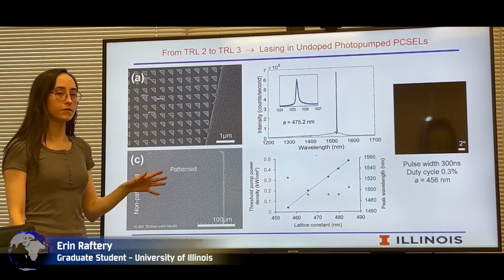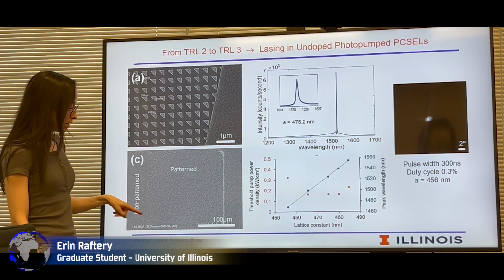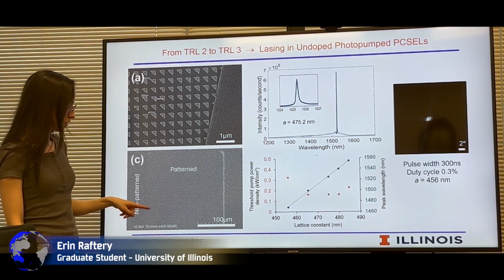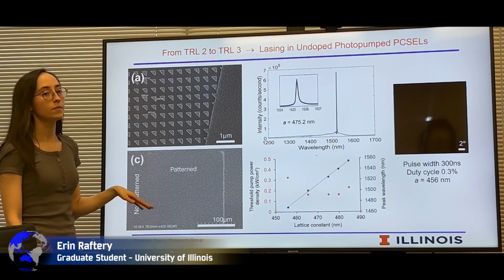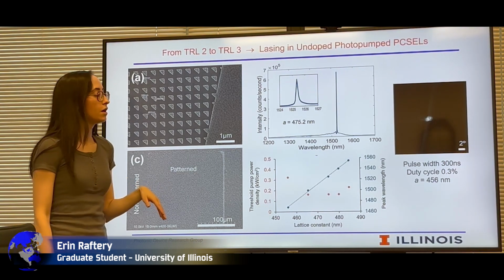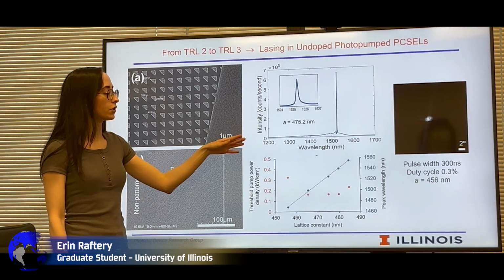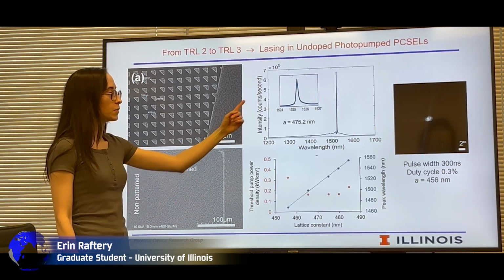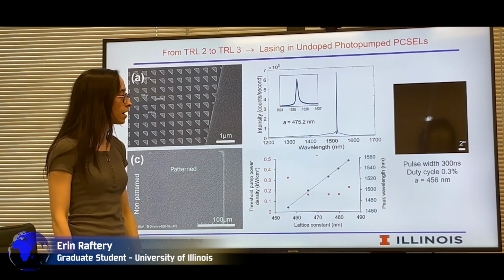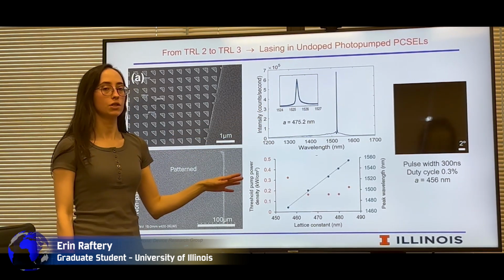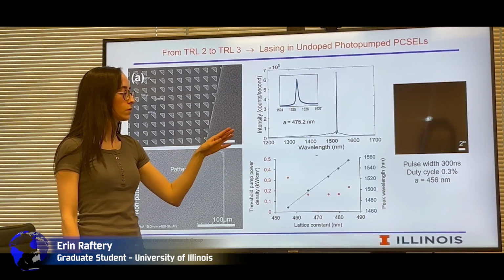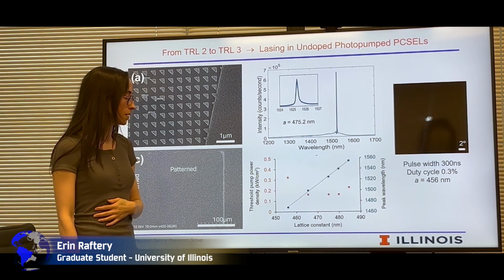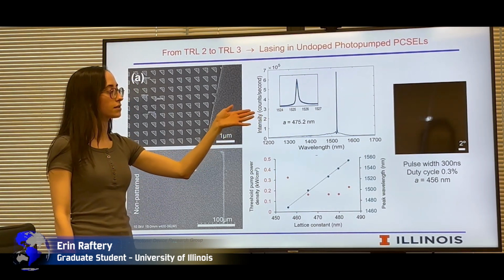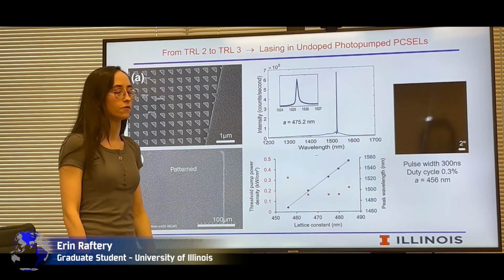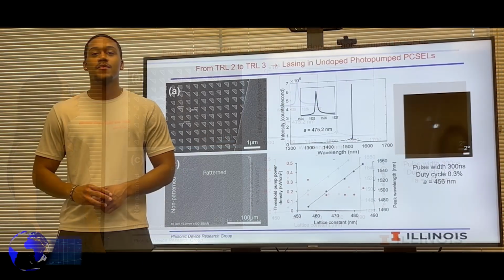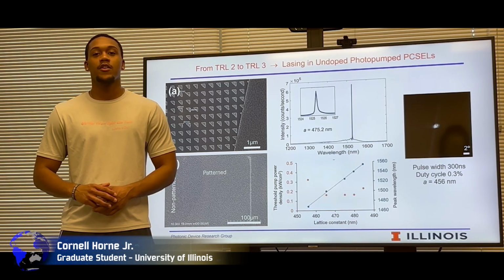We demonstrated successful smooth overgrowth of the surface. This is the pattern region of the pixel, and this is the non-pattern region. We can see from the SEM view that the surfaces are very similar. And we found, scanning over several different lattice constants, we are able to see lasing emission with a narrow line width. And that emission wavelength scaled with the lattice constant, which is what we expect. And we were able to see this on-axis center beam in the far field profile that's projected onto a screen. In the third increment, we will demonstrate lasing in doped photopumped pixels.